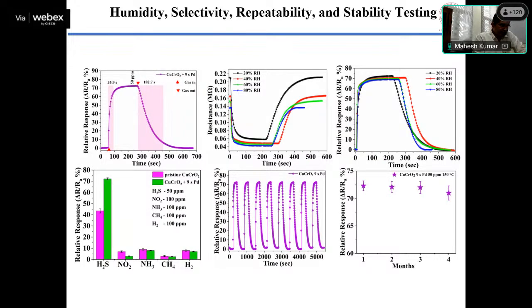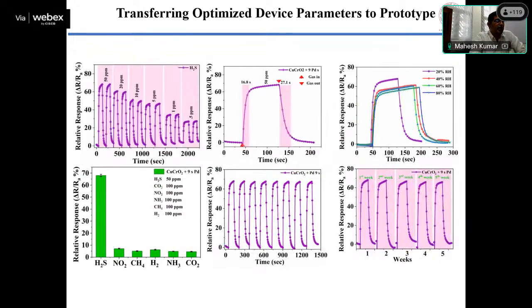These are the other parameters: selectivity, which is highly selective. The response time is around 35 seconds, but if you want to use it a second time, we have to wait around 3 minutes, about 180 seconds. In gas sensors, this is acceptable. And these are the other performance parameters, such as humidity. Next, we transferred this to a prototype on an alumina tube, performed all these measurements, and found it is highly selective towards H2S.